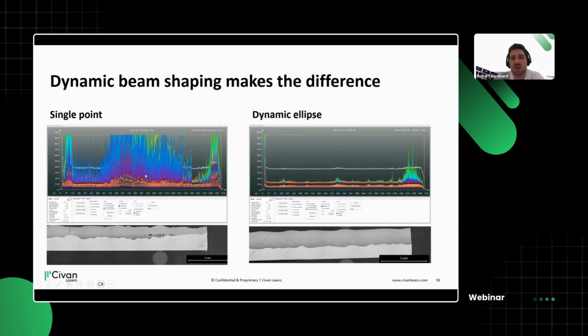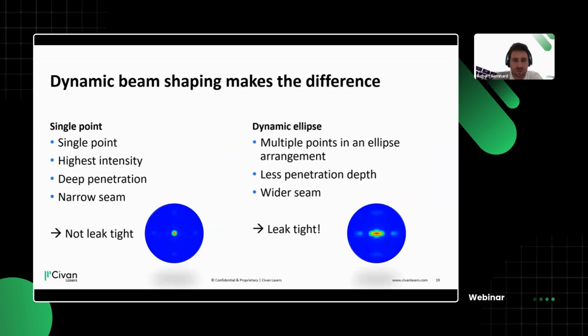So the signal you see here is back reflection in different wavelengths from the process zone itself. And if we switch to our developed dynamic ellipse, it almost becomes good. So this is something manageable where in serious production we can specify a threshold and just see that this is a very stable and good process, I would argue. So to underline this for our Civan Lasers demonstrator, we have this dynamic ellipse that has less penetration depth. The width is wider.